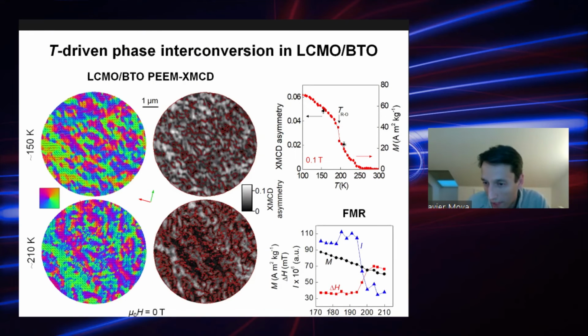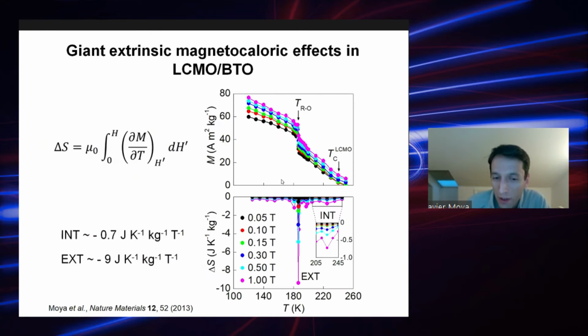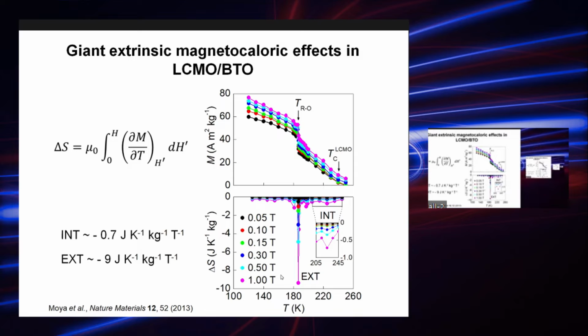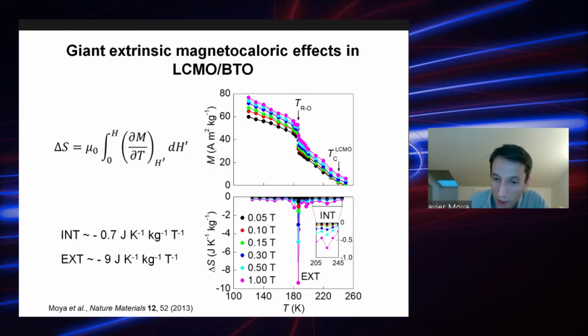You can basically get the same data using ferromagnetic resonance, and then you can calculate the caloric response using the Maxwell relationships. Interestingly, near this extrinsic magnetostructural transition that is driven by strain coupling between the substrate and the film, you can get magnetocaloric effects that are an order of magnitude larger than the intrinsic caloric effects that happen near the Curie point of the film itself. Of course, this peak is very narrow, so the applications are not going to do anything. But from the science point of view, it's an interesting example of how you can use stress to tune the properties of existing magnetocaloric materials and increase the performance.